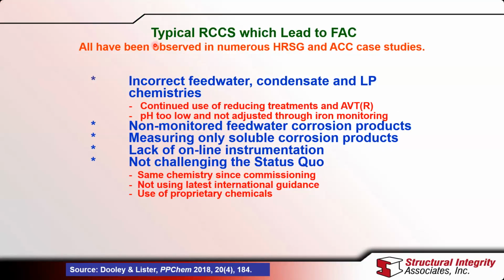So these are those repeat situations which lead to FAC. These have all been observed numerous times. And generally what we find is that FAC results from incorrect feed water, condensate, and LP chemistries, with the most common one being the continued use of reducing treatments. And we call this AVTR, all volatile treatment reducing. For the two-phase part, we generally find that the pH of operation is too low and not adjusted or monitored by monitoring the iron to see that the iron meets those guideline values that I showed you before.